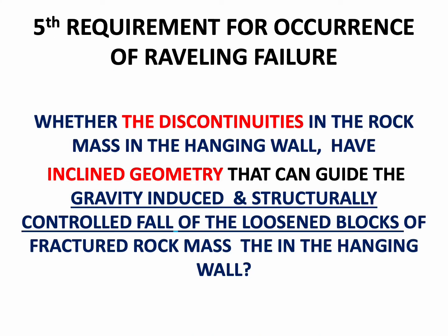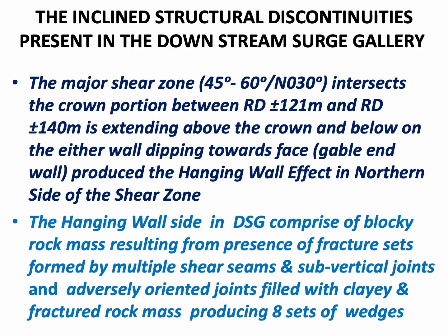Now the fifth requirement of the occurrence of the raveling failure was whether the discontinuities in the rock mass in the hanging wall have inclined geometry that can guide the gravity-induced and structurally controlled fall of the loosened blocks of fractured rock mass in the hanging wall. The inclined structural discontinuities present in the downstream surge gallery: the major shear zone is 45 degree to 60 degree inclined with north 30 degree orientation, which intersects the crown portion between RD 121 to 140 meters, extending above the crown and below on either walls, dipping towards face. This produces hanging wall effect in the northern side of the shear zone.